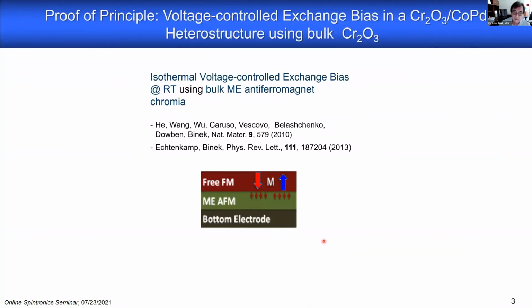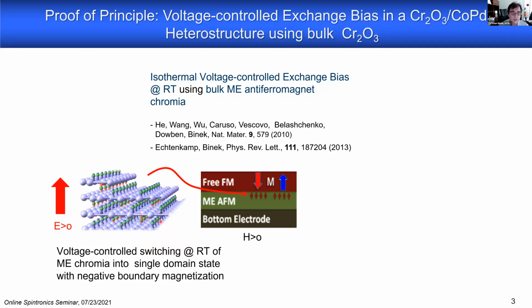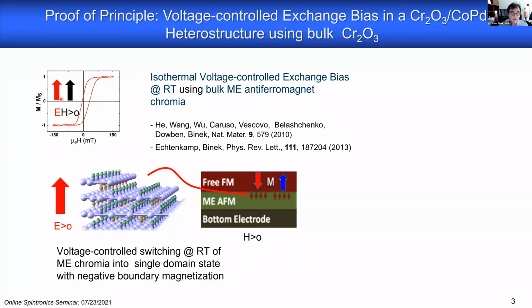Let me show you now our proof of principle in a system made out of a bulk magnetoelectric chromia, where we put a thin film on top deposited by MBE. And what I just showed you is happening here. You see a cartoon of the atomic and spin structure of Cr2O3. You see here this boundary magnetization, which again is an equilibrium property. So it's also present, that's a nice thing, if the surface is rough and has these steps here. It has been selected in a particular single domain state. So the exchange bias accordingly is on one side here. In this case, if the product is positive, the exchange bias field is positive.